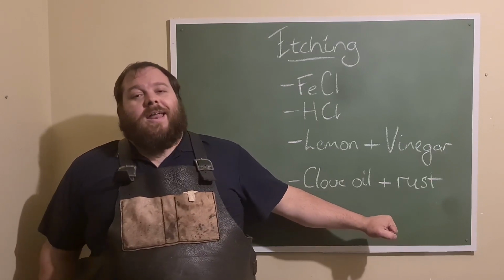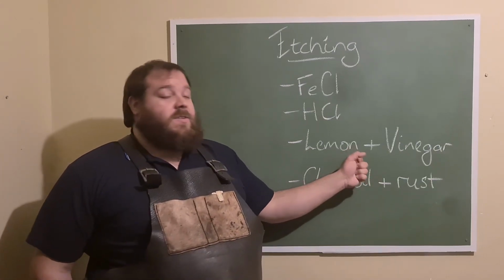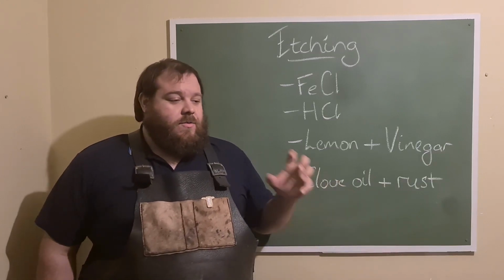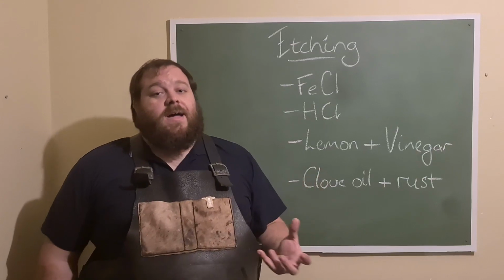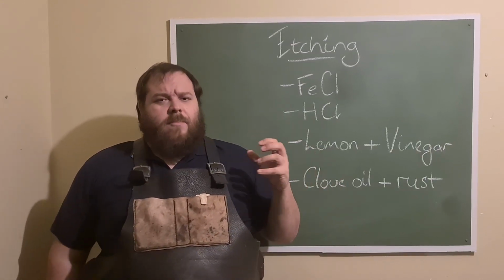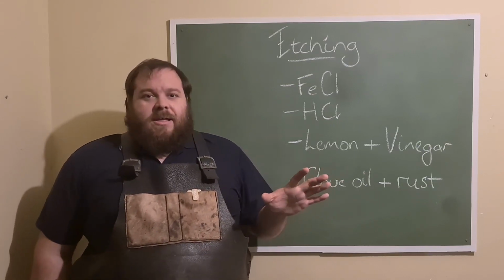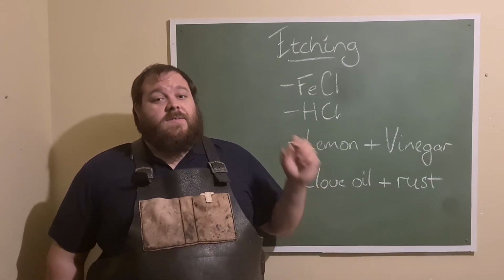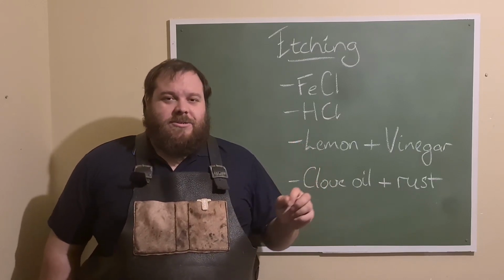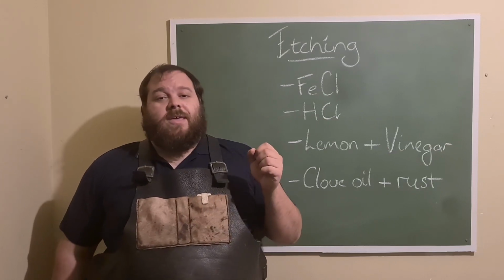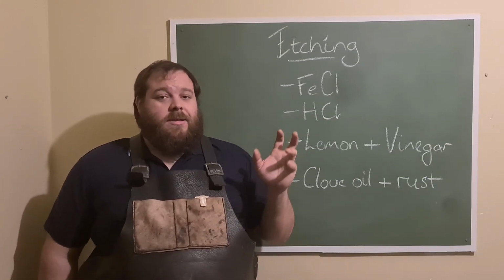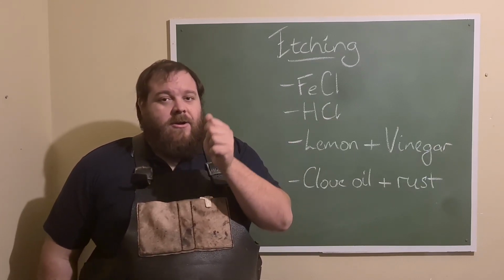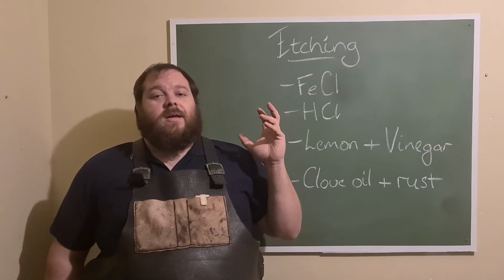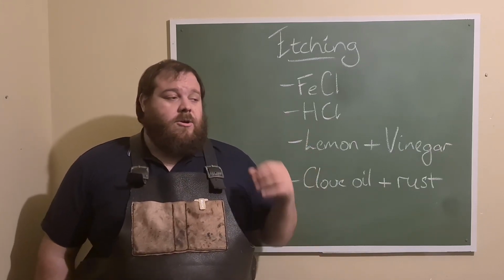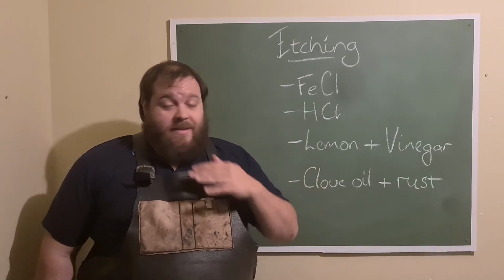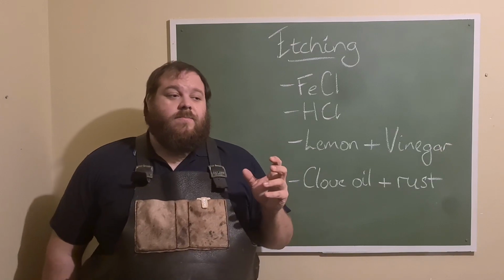I do believe, and I haven't got evidence for it, but I do believe that they use some form of citric acid mixed in with their clove oil to create that whitening effect, but that is how most katana are whitened. People say that katana Hamon are only there through polishing. Not entirely true. There is specifically, in some cases, the Yuzuya stone is used to polish certain segments of the Hamon to create an artificial ashi. So they actually use the stone lightly in areas to create that ghost-like effect because the Hamon itself, the quench itself, did not go to plan. So there are people who do polish in, and this is traditional, polish in parts of their Hamon. So don't be afraid to try that as well.